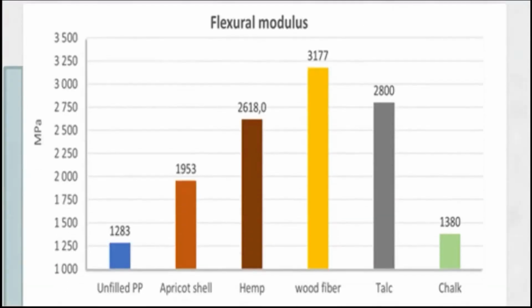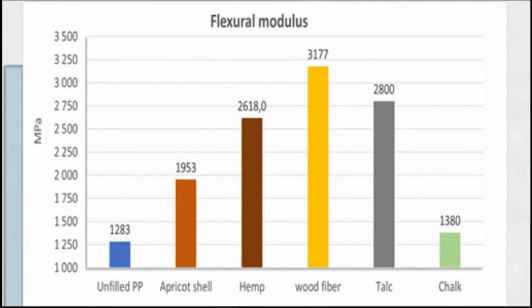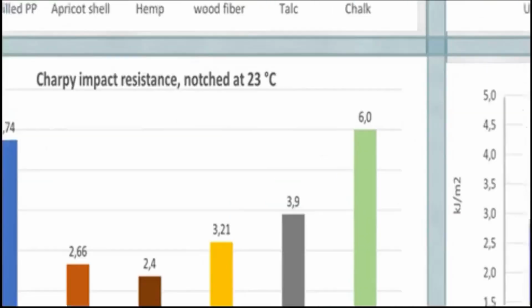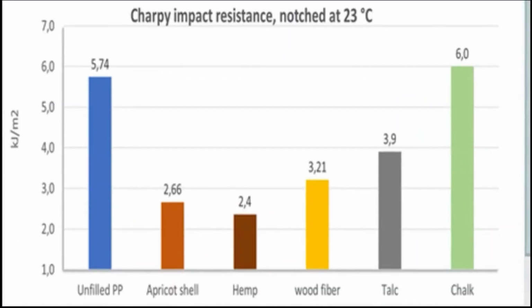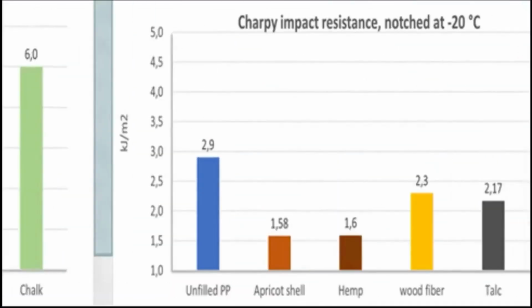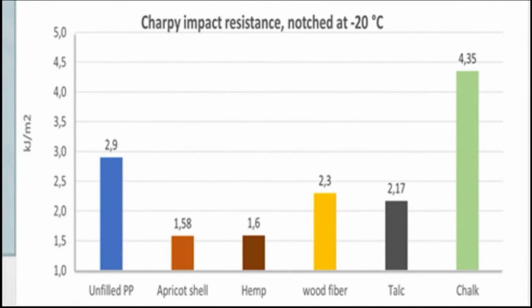In the case of flexural modulus, there are significant differences between the fillers. Wood fiber increases the modulus the most, better than talc. Hemp is almost the same as talc, apricot shell is the last. In the case of compounds with natural fiber filling, the sharp impact properties decrease; the effect of inorganic fill in composites is better.